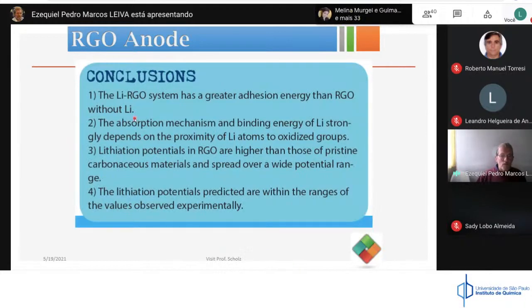Well, this is some of the conclusion concerning the system. If you lithiate the structure, you have a higher adhesive energy. The absorption mechanism and binding depend on whether lithium is absorbed in proximity of an oxide group or not. We can also conclude that the lithiation potential of the reduced graphite oxide is higher than that of the pristine materials. It's also interesting to see that the lithiation potentials you get are within the range of the values that are observed experimentally.